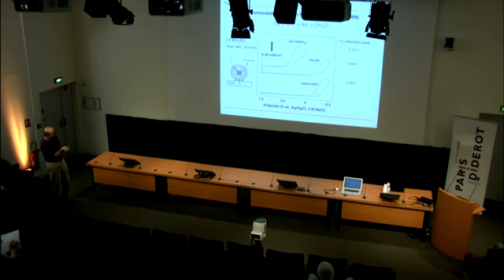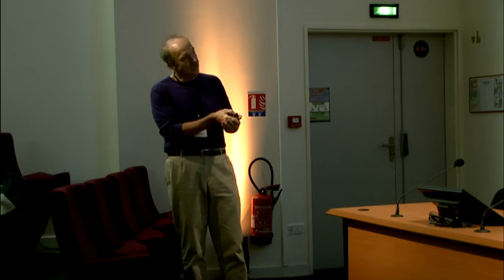Now he puts a 40-atom platinum particle inside the dendrimer, exactly as shown here. He does the same experiment, and there's a shift of about 600 millivolts towards more positive potentials, indicating that the platinum nanoparticle is electrocatalytically active. Okay, so this was a really important experiment for us because it showed that this basic concept was going to work, and that this is an accurate, if somewhat simplified, picture.